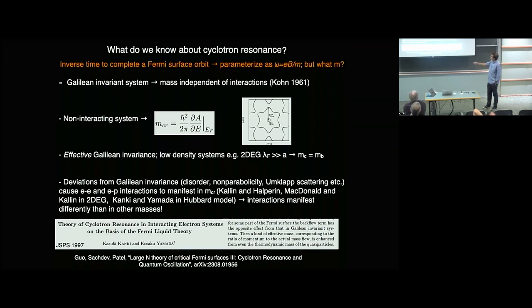If we have some system with effective Galilean invariance, maybe like some low-density system where Fermi wavelengths are really, really large as compared to the lattice constant, then it's been shown, let's say in a 2D electron gas, that the cyclotron mass is not the bare mass, but you have this effective Galilean invariance where it's essentially the band mass. And so this has been exploited in semiconductor systems, 2D electron gases.